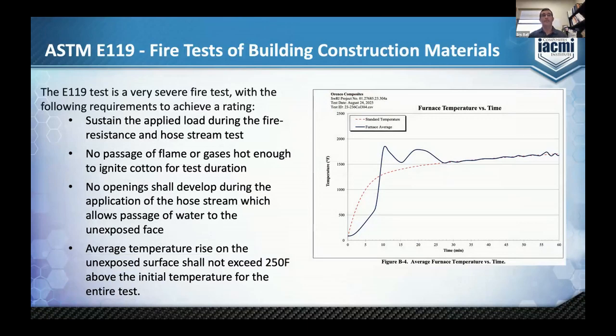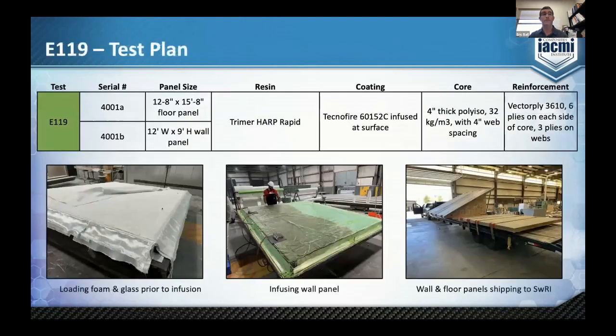So here, the full E119 test is pretty large, and a very severe fire test. It has to sustain an applied load during the fire test, no passage of flame or hot gases, and no openings can develop. And there's a hose stream test at the end that can't allow water to pass through. And again, you can't exceed a 250-degree temperature rise. Here, just an example of the panels being fused. We did both a floor test and a wall test. The floor panel was 12'8" by 15'8", and the wall test is 12 by 9. We went to a 4-inch thick panel. The mini tests were only 3 inches, and we did that because we wanted to achieve an hour rating, because that's a meaningful value in the IBC for a lot of standards.